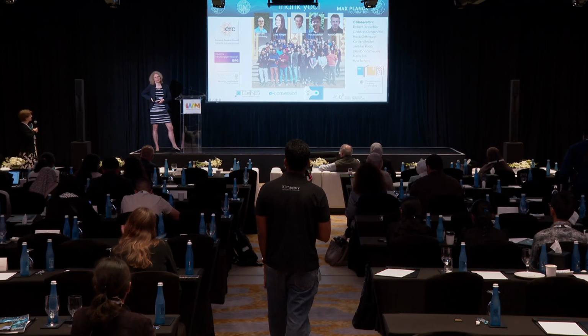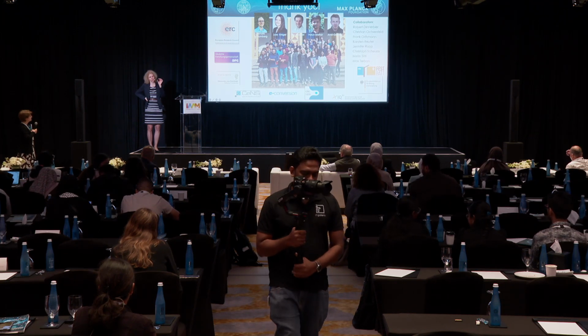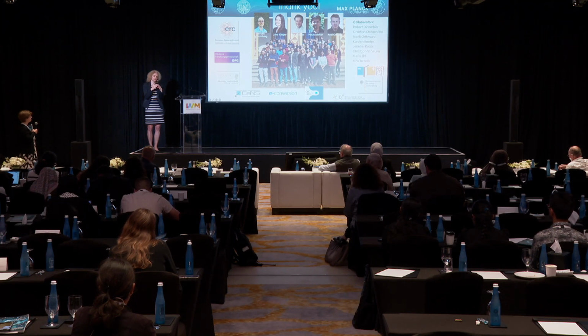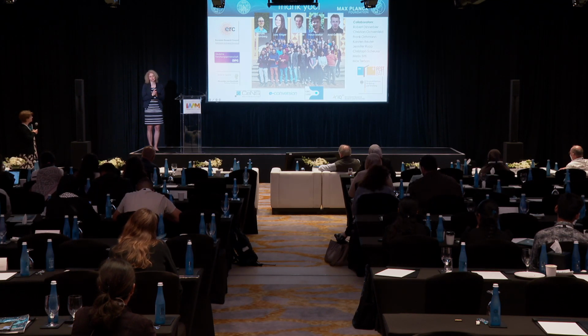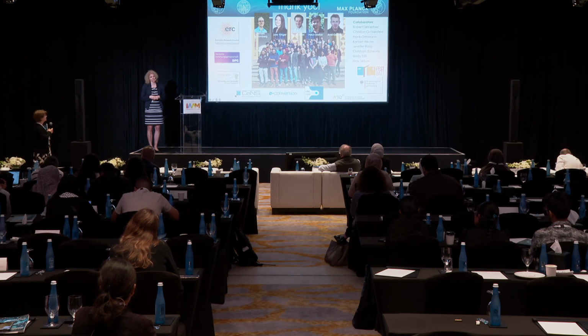So we do have defects in these systems, but they are most certainly not responsible for the charge trapping. The idea basically is, and I think it really helps to think of the system as a photointercalation system, that the heptazine units are the sites where the electrons are trapped. And this works so well because heptazine units are very electron poor, so they can receive electrons and delocalize them, not just across one heptazine unit; there's most likely a delocalization across about two heptazine units. This is what we know from EPR. At the same time, the charge balance occurs through the cations that intercalate into the system. So basically, charge trapping is a kind of photointercalation process, as we see in several oxides. I'm not sure if that answers the question, but we can also discuss afterwards.